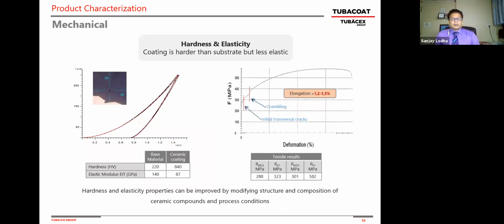This slide is another interesting slide that shows on the left side the load displacement curve. When you put a certain amount of load, how is the surface reacting? And when I look at the hardness of the coated tube, that is 840 Vickers number compared to 220 for the base material. So I'm able to bring a hardness 4 times higher than the base material. But it does come at a cost to pay. And that cost is on my right side. If you look at the elongation, once you coat the tube, you can elongate up to 1.5%. And beyond that point, if you were to do physical bending or physical elongation, then there will be damage to the coating. So there is a price to pay.